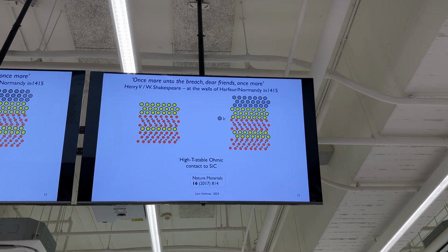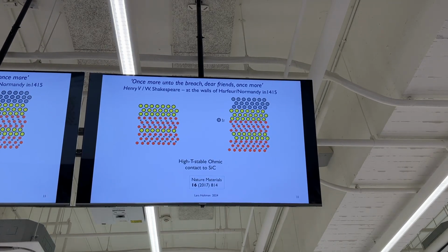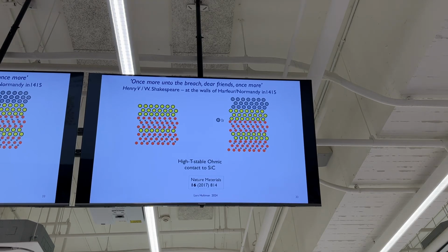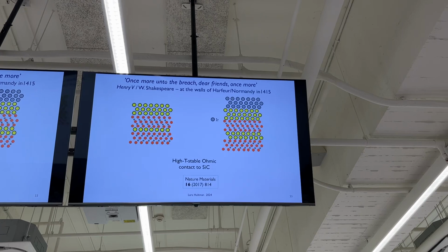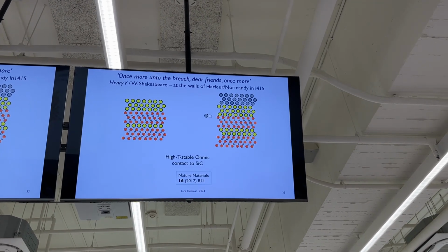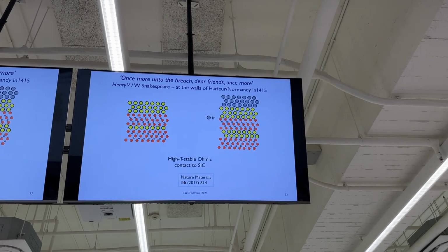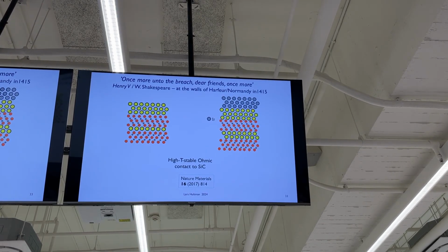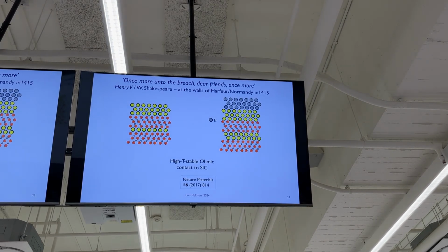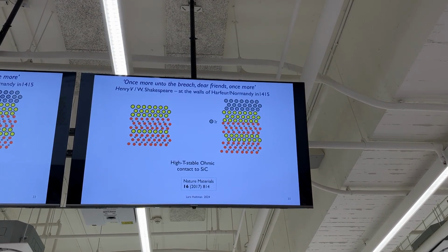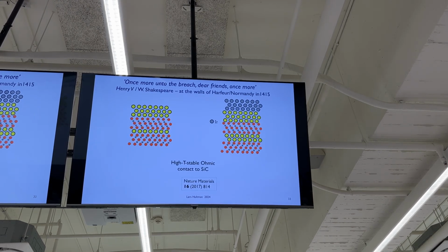I should also say that what brought us onto this strand of research is that we wanted to make ohmic contacts to silicon carbide. Silicon carbide is a wide band gap semiconductor. It's used in power electronics. It can get hot, warm. So you need ohmic contacts, which are not easy to get applied to silicon carbide. So we thought that the MAX phase, which is a conductor, has a good lattice match to silicon carbide. So we started with that, and we wanted to add connectivity for the pads with gold.